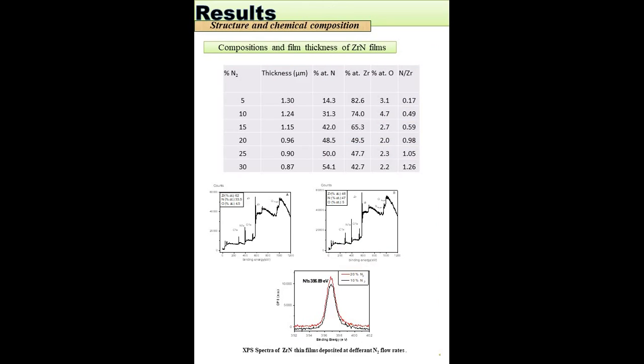Now let's see the results. From the XPS spectra, we can see clearly that the increase in nitrogen flow rate delivered an increase in nitrogen content and a decrease in zirconium content in the films, where film thickness was found to decrease gradually with increasing nitrogen flow rate. A ratio of about 1 was obtained at 20% nitrogen flow rate.